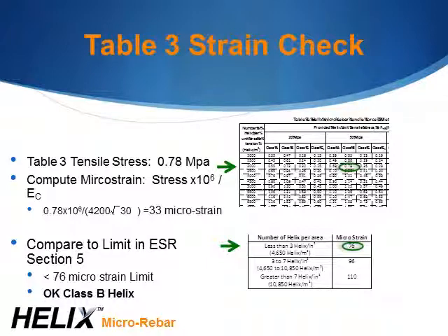So for SI units, that's 4,200 times square root of f'c. In this case, we calculate that the tensile strain is 33 microstrain. Once we have that, we compare it to the limits that are established for tensile strain in section 5 of the evaluation report. In this case, it's 76. So since that 33 microstrain is well below that strain limit of 76 microstrain, it's okay for class B. What that means is that we are safely below the strain limit that we've measured is required through the direct tension testing approach for our class.